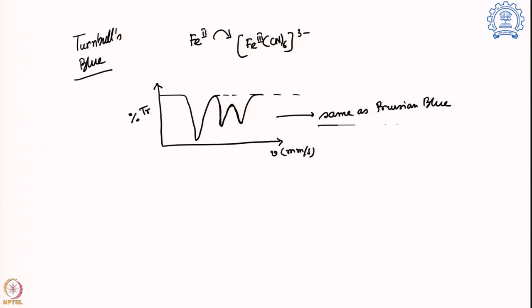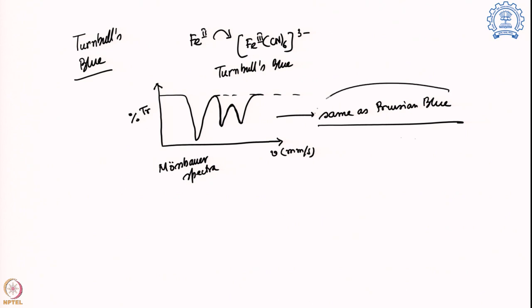So they have similar Mössbauer spectra. If it has a similar Mössbauer spectrum, this is for Turnbull's blue, and this is the same as Prussian blue. So it is saying that I still have an iron 2 low spin system, and I still have an iron 3 high spin system. So how is that possible?